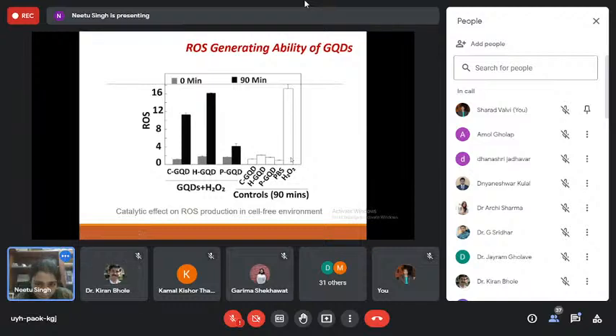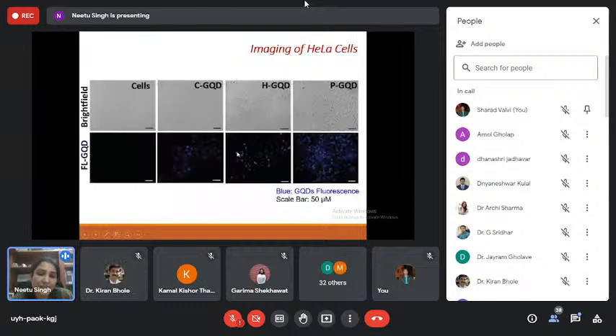So as I said, we focused on looking at the ROS generating ability. So you can see that with your, PGQD is the polymer coated. If you do not have polymer coating, the ROS is increasing after 90 minutes. Whereas if you have a polymer coating, see how dramatically low this ROS generation is. We were very excited and we started looking at whether this will be replicated. So this was done in a test tube. So will it be replicated with H2O2 as the ROS generator or the free radical generator?